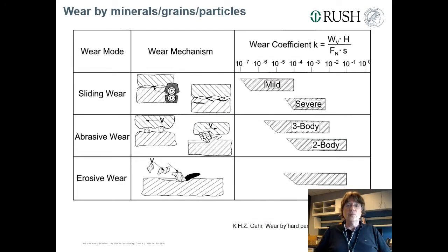So Zum Gahr put that together. He mainly worked on abrasive wear, and he more or less introduced what we call the sub-mechanisms. And in his books and some published papers as well, he took this K value, which comes from the Archard equation. And so he showed where laboratory wear normally could be located when it comes to these K values. So the abrasive wear is mostly around here. In severe wear, sliding wear is roughly the same, while in mild sliding wear, it could be smaller.